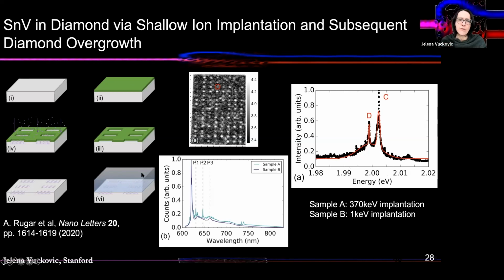And recently, to overcome that, we've come up with this shallow ion implantation and subsequent diamond overgrowth method, where we dramatically reduce the energy for implantation from hundreds of kilo electron volts to 1 kilo electron volt, which means that you can also use a very simple mask, a single layer resist mask. You bombard high purity diamond with these ions. That incorporates them at the desired positions, but of course they're positioned very shallow relative to the top surface, which is also not desired for final devices, which is why we end this process with overgrowth of another high quality diamond layer. That way you end up with your color centers deeply embedded inside of the structure.